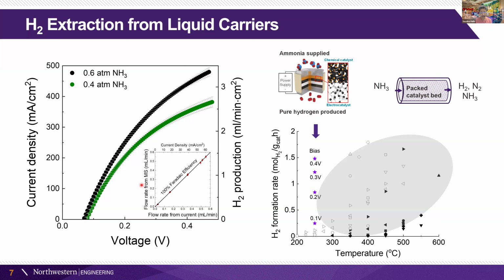What you can see on the left is the current density as a function of the voltage that we apply. And from that current density, you can calculate the hydrogen production. And we also measured the hydrogen production directly using mass spectrometry, and we could confirm that the hydrogen production was exactly equal to the number of electrons that we delivered, and that tells us that our system has 100% Faraday efficiency.